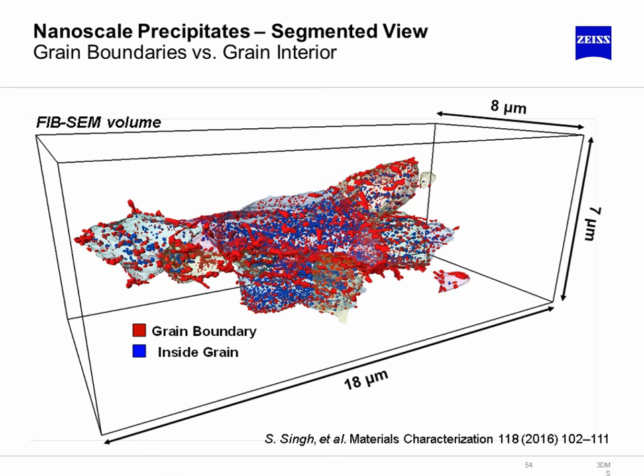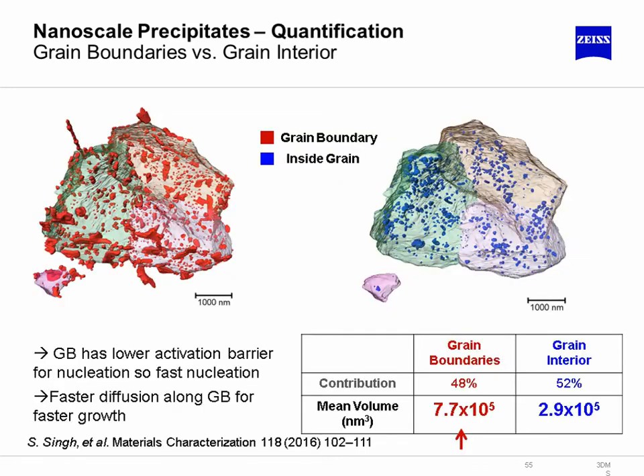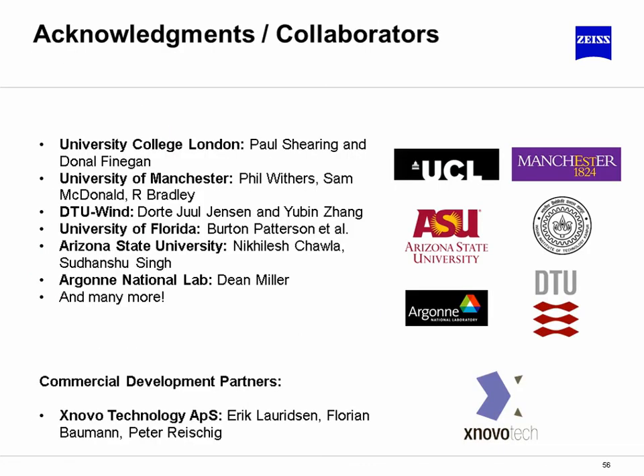The red precipitates are those that are found at the grain boundary. The blue ones are those that are found inside of the aluminum grains, and now we can statistically compare these to one another and measure, for example, that the mean volume is more than twice the size at the grain boundaries as they are on the grain interior. And this type of information can really feed models. This is expected. I think you have obviously faster diffusion along the grain boundaries, and they act as a nucleation site or faster nucleation site. So while that's expected, calibrating the exact dimension difference is important and fed in by this type of information.